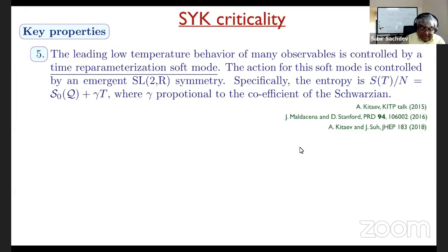So it turns out this model has a linear in T specific heat, just like a Fermi liquid, but with the coefficient gamma. And this gamma comes from these time reparameterization fluctuations. So it's very different from the usual origin of linear in T specific heat, where you have free fermions around the Fermi surface. Here it's time reparameterization fluctuations. Of course, in a Fermi liquid, S0 of Q is 0. Here, this is non-zero. And that's something we had understood earlier. This was understood by these people, the second term.